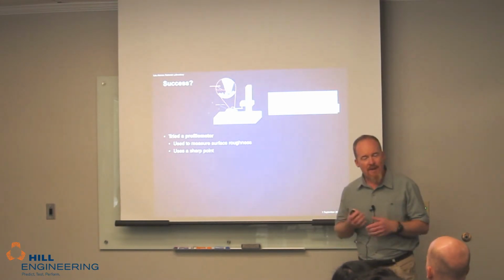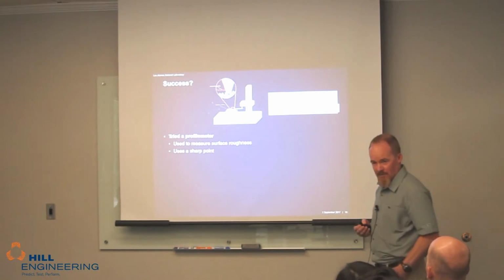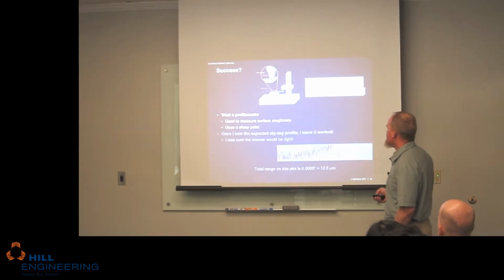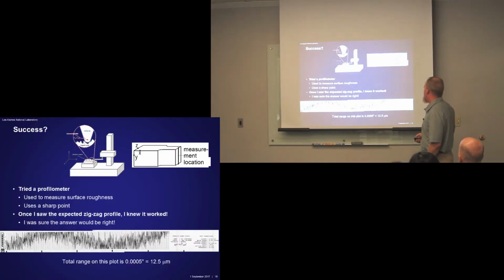I grabbed another picture here. So I had to measure that surface height. I didn't know how to do that either, how to get a surface height map. Asked around the lab, and somebody said, well, I've got a profilometer, one of these things for measuring surface roughness, where you've got this stylus with a fairly sharp tip, and you drag it along the surface to measure surface roughness. But the guy said it also did absolute measurements, right? It didn't filter out the long range thing. So tried that, grabbed half of the specimen, measured along the surface, and I got this result.